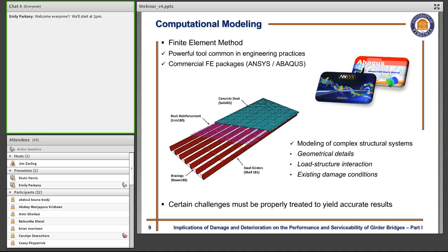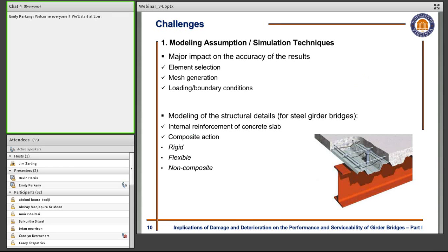And the challenge with this approach is that certain challenges must be properly treated to yield accurate results, and that's a very important thing. It's kind of the mindset of if you put garbage in, you get garbage out, and so it's actually very important that you try to model the actual phenomena that exist. So some of the modeling assumptions and simulation techniques that need to be considered, some have major impacts on the accuracy of results, including things like element selection, mesh generation, loading and boundary conditions are critical. For these bridge systems, we need to be careful and cognizant of modeling structural details, such as internal reinforcement of the concrete slab, composite action of the system, interaction between the deck and the girders.